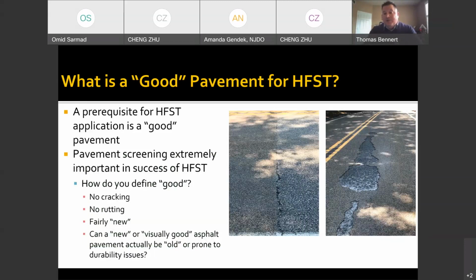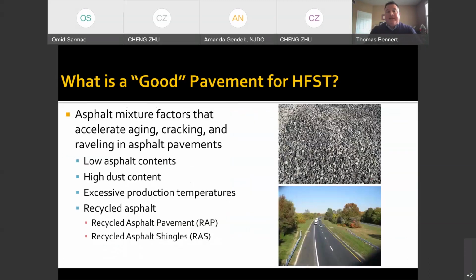You can see some pictures over here on the right. This is what happens when an HFST section goes bad. The picture on the left there actually shows the transverse location where the HFST stops. And you can see it actually creating a transverse crack in the pavement. More commonly on the right, what you see there is what we would call a shallow delamination, where you actually have chunks of this HFST being pulled up. The fact is that we can actually have a pavement that appears to be in good condition, but not be a very good durable pavement.